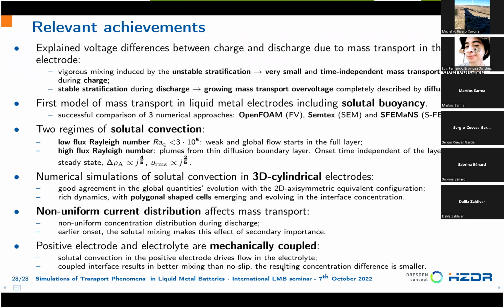And we also study what happens if the positive electrode and the electrolyte are mechanically coupled. And what we saw is that solutal convection drives a strong flow in the electrolyte, and the coupled interface allows better mixing than the no-slip one assumed in the first part of the study.